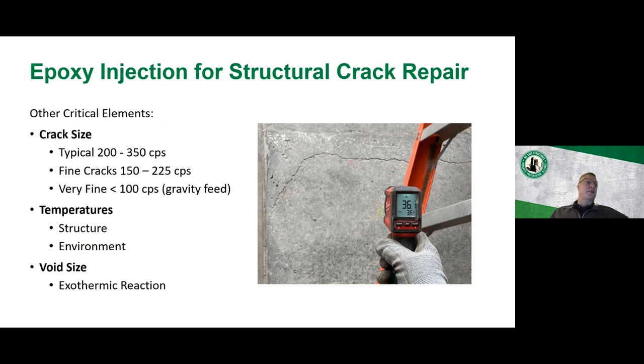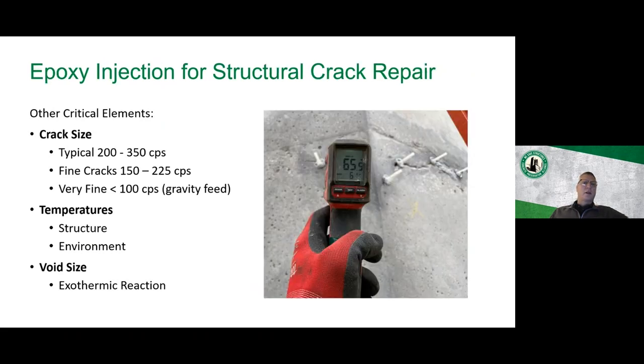So in this photo, I show the pre-repair process. That concrete is 36 degrees Fahrenheit, so just right around maybe 1 degree Celsius. Too cold for the epoxy resins to be able to bond to. So what had to happen was heat and covering had to be applied for this repair before we could get started. And so we were able to raise the concrete up to 65 degrees Fahrenheit. And then we were able to start adding our ports to be able to do the repair. So these are things to pay attention to.